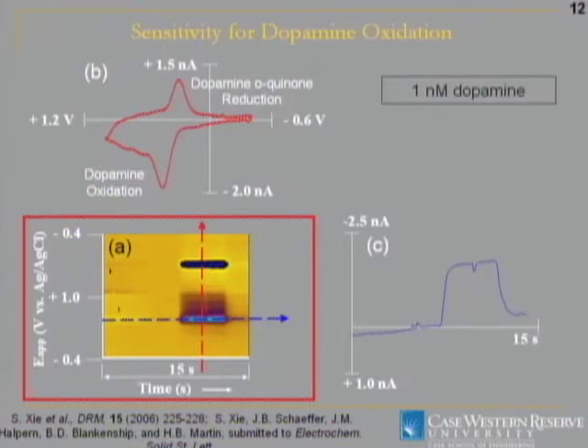And so what we can do is then look at the voltammetry over time, and whenever we see a change in the color, that means the current at that particular spot has changed. So if we were to take a slice at any given potential over time, you can see the current for dopamine go up and come back down. In terms of what that current corresponds to, you have to look at the voltammogram directly and identify the particular peaks which have been independently identified as dopamine oxidizing and dopamine being reduced.